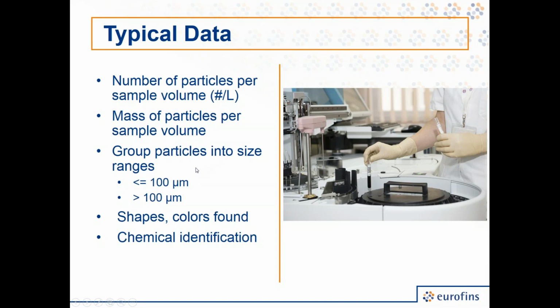In addition, though, we will provide information in terms of particles found in 2 different size groups. Now, in this case, we typically pick stuff that's less than or equal to 100 micron and then greater than 100 micron. But these two categories are arbitrary because we can adjust those as needed. So that's pretty straightforward to do. And again, there's no standardized way of reporting the data. It just depends upon the study that's being performed, the requirements of the data use. In addition, we'll come up with the shapes of the materials found, and also the colors that are found.